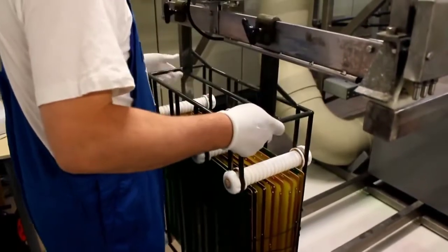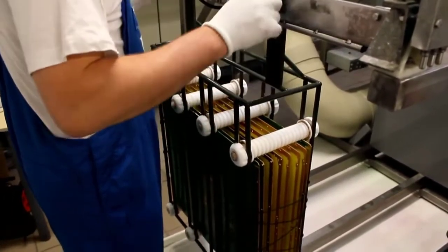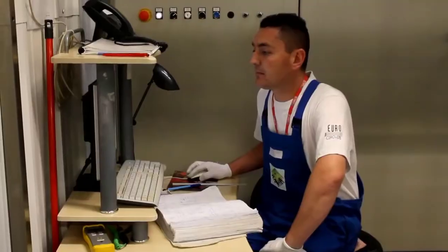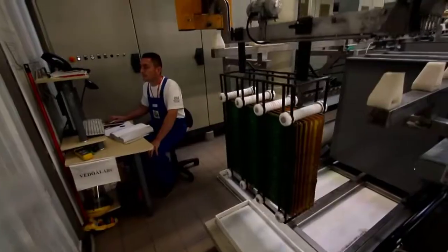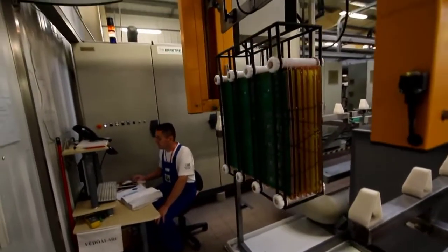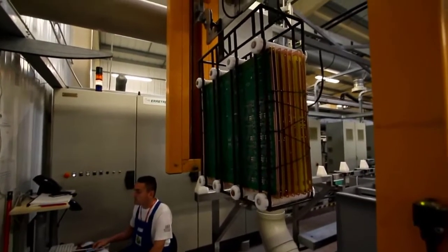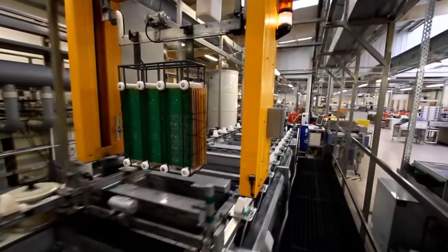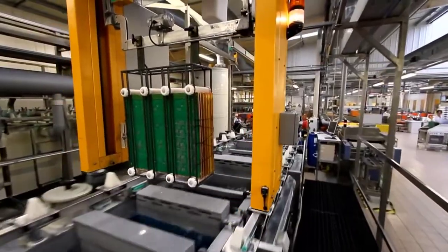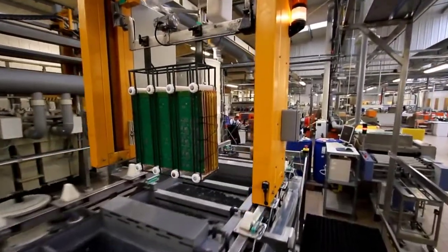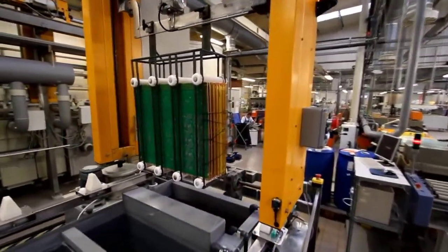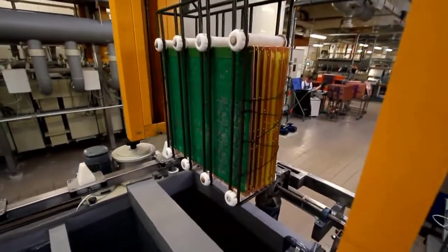On this line we chemically deposit first nickel onto the copper and then a thin coating of gold over the nickel. This is a chemical process needing no electrical connections. The line is fully automated, moving the panels through a series of tanks which clean and sensitize the copper surface and then deposit about 5 microns of nickel and 1/10 of a micron of gold.